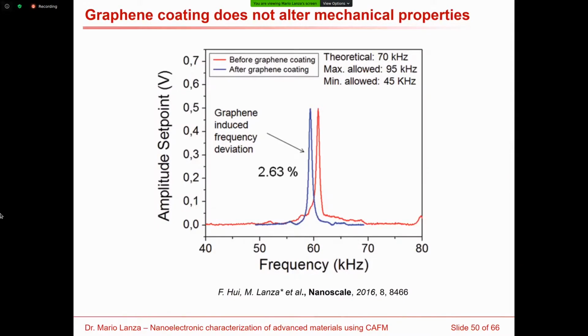We analyzed the change in the resonance frequency of these tips, and we observed that the graphene doesn't change the mechanical properties of the tips. Of course, because it has negligible mass, and this doesn't alter the mass of the cantilever, and therefore it doesn't alter the mechanical properties like the spring constant or the resonance frequency.